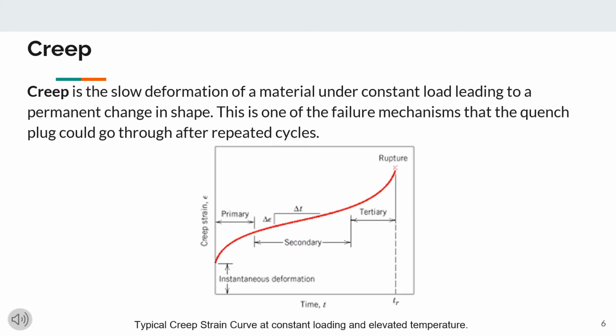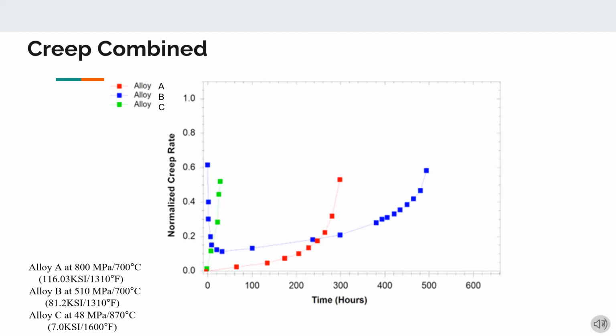Creep is the slow deformation of materials under constant loading or cycles. Due to the number of cycles that the quench plug will be going through, we know that creep failure will be its primary failure mechanism. So we wanted to compare the creep rates of our three alloys. As we see here, we have the normalized creep rate for each quench plug material versus time, with the test conditions shown in the bottom left corner.